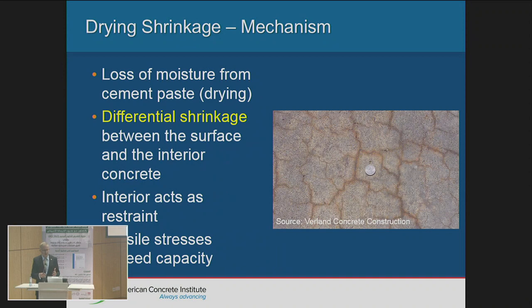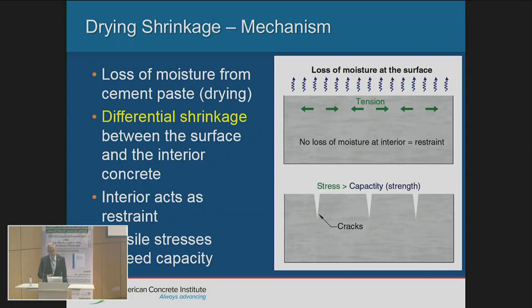So in general, why does concrete crack? It's mainly because if you have fresh concrete, because of the loss of moisture, okay? You lose moisture much faster at the top than in the inside, especially when you have a climate or environment like here. You have very hot climate, concrete is still fresh, you still have water down below, but at the top, it dries. When it dries, what happens? It tries to shrink, right? Whereas internally, it still hasn't shrunk yet. So you get those fine cracks at the top, where the tensile stresses in your concrete exceed its capacity, as we see here. So you get loss of moisture, and you get the cracking.